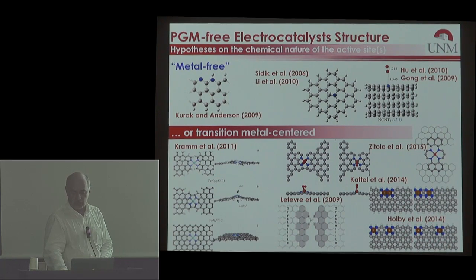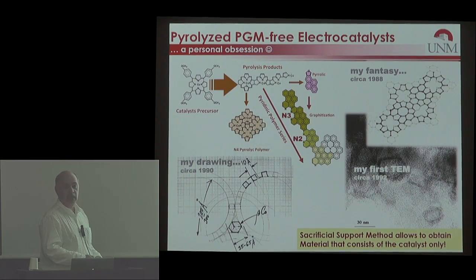So let me start with what we really know. What we really know and learned through the years, and I have been burning this material since '88 or '87, is that if you start pyrolyzing macrocycles or other molecules that contain nitrogen and carbon, you're walking at least one of three pyrolyzation paths. So depending on the temperature-time trajectory, you can walk through polymeric condensation or pyrrolic transformation, or you can actually achieve pyrolization towards graphitization of the material. And that most complex path is the one that actually yields the catalyst.